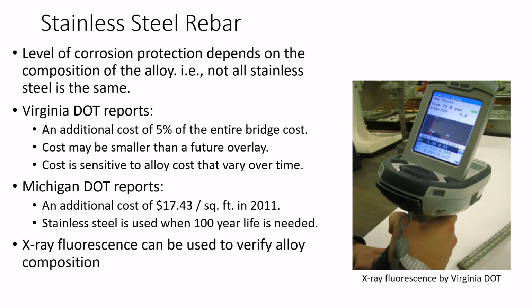So Virginia and Michigan DOT reported the cost of stainless steel. Virginia reported about a 5% additional total cost if they use stainless steel in their deck, and their justification is that that cost may be smaller than a future overlay. And then Michigan DOT reported about a $17 per square foot increase in cost back in 2011.